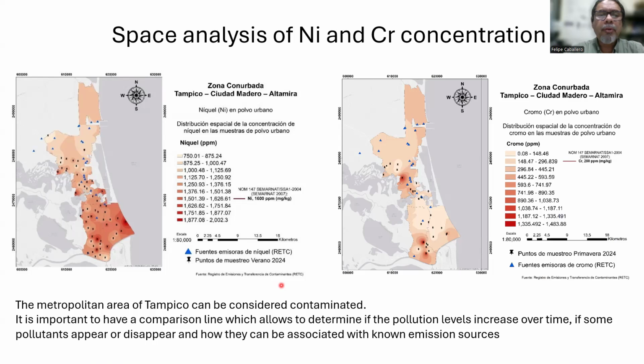After X-ray fluorescence, we performed a spatial analysis of nickel and chromium concentration. The more intense the red color is, the higher the relative content of nickel, which, as you can see here, is very concentrated in the region where the refinery is. Nickel is one of the metals associated with oil. It's a marker, together with vanadium, of the type of oils that are refined and burned. And there is some nickel concentration near the coast of the lakes here, and some points here. In the case of chromium, the hotspots are mainly concentrated in the industrial corridor and around the river, and interestingly, near the city center where there is a commercial port.